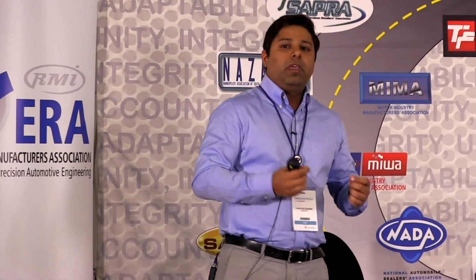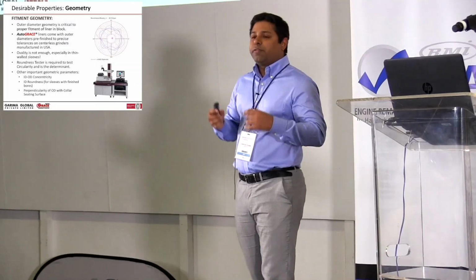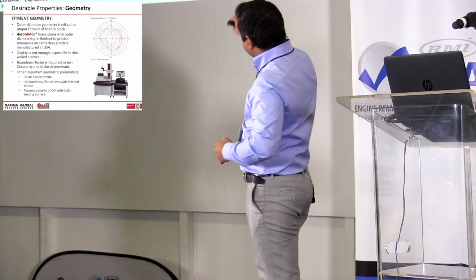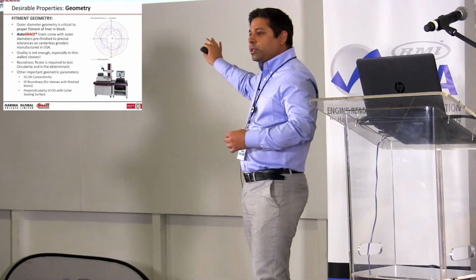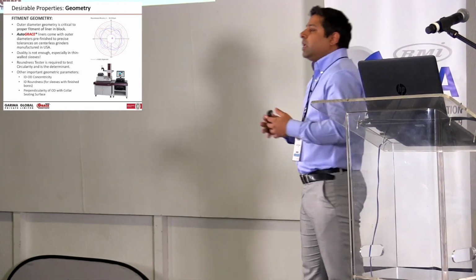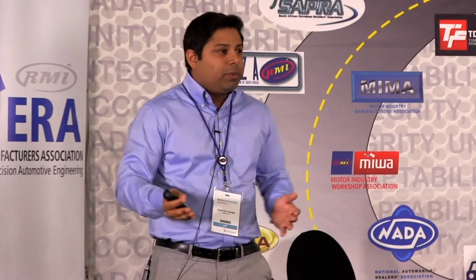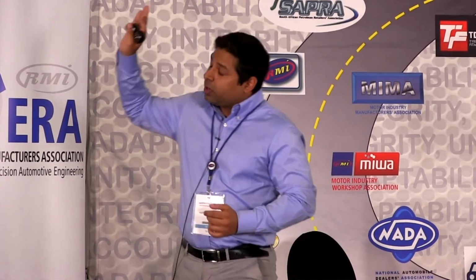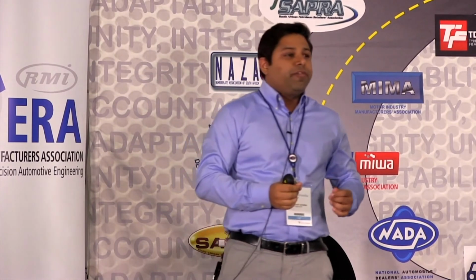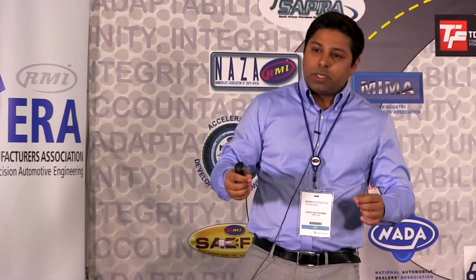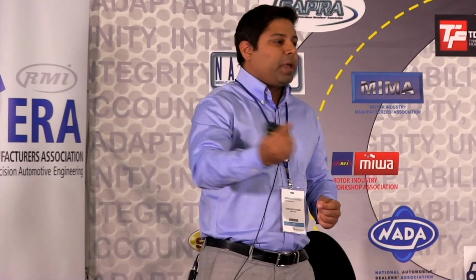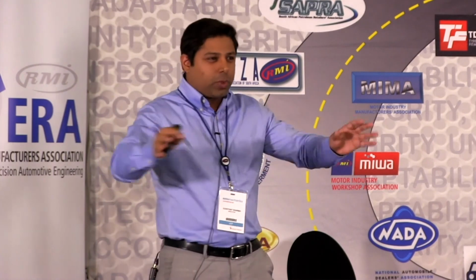Ovality is not enough. If you really wanted to test the circularity of the outer diameter of a liner, you would have to put it on a roundness tester, which most of the shops don't have. Because for thin-walled sleeves, the ovality can get disturbed even during transportation. But what this roundness tester does is, instead of measuring diameter at just 2 or 3 points, it takes thousands of points across the periphery of the liner, and then it does a root mean squared and all those cool formulas, and it will give you a circularity. And a circularity of less than 30 microns is more than enough for most automotive applications.